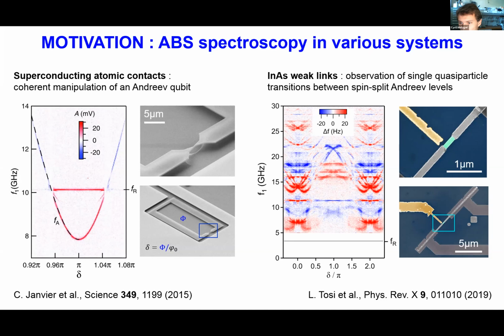However, for InAs data, you see that we also measured similar features of change of sign along the line intensity. However, in this case, the transitions were very far from the resonator, which was at 3 gigahertz only. And so this really convinced us that we were in need of a more general theory that would go beyond the dispersive regime to be able to explain such data. This is what motivated this work that I'm quickly reviewing today.